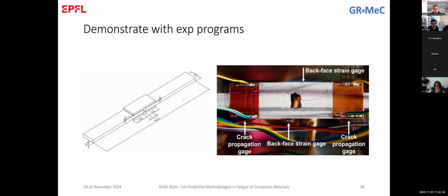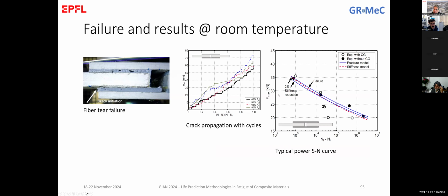So we did this testing in a lot of different types of loading. As we said before, we measured the crack propagation with cycles. The crack initiated here and propagated with cycles in this trend, a kind of linear trend up to failure. And also we created SN curves. And we again saw that these SN curves can be fitted by typical power law equations. I will discuss later on about this stiffness reduction. It's another type of SN curve that we introduced.